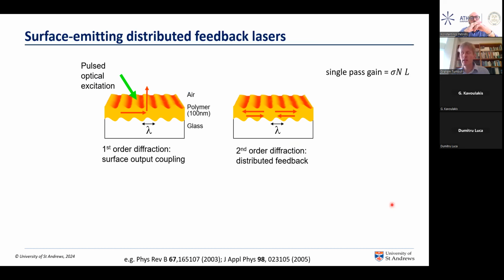So this is the typical common resonator structure that's used in an organic laser. In a conventional laser, you have a gain medium in the middle and you have two mirrors at either end, and the light travels backwards and forwards between the mirrors through the gain medium to build up the laser field. In this case, we embed a diffraction grating into the side of our polymer waveguide, which, as light travels through the waveguide, diffracts it. Very often we choose a period of grating such that a first order diffraction will provide a surface emitted output beam from the laser, while the second order diffraction reorients the wave through twice the angle and provides the in-plane feedback within the film. And so these are distributed feedback lasers.